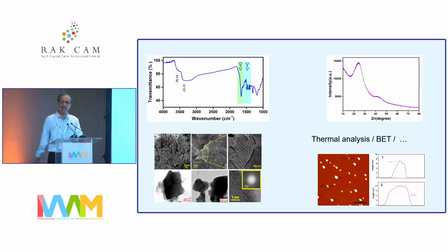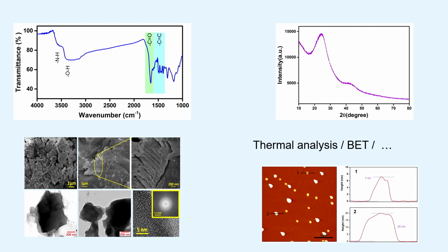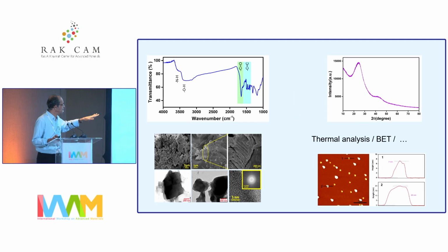But once we have this kind of a polymer, we try to characterize the way we do, and the first thing that we look at is the solubility. It is not soluble in the battery solvents, and that's the basic advantage for us. So once we have that, we try to understand the electrochemical properties after looking at the physicochemical properties that are shown here. For some reason, it forms a layered structure, but then it's an amorphous material. It's possible to have it in a solvent and exfoliate it as well, and then have a thin sheet of this polymer formed.